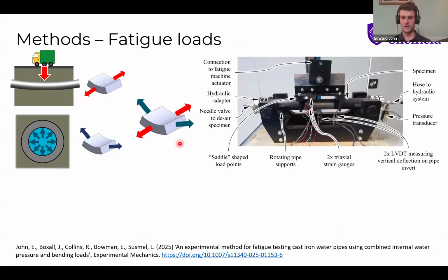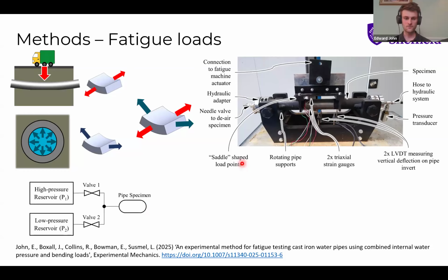So to apply the bending load, we built this piece of 4-point bending equipment. You can see a pipe specimen in the middle there. And so we can bend the pipe and create a high stress region at the bottom in the middle there where we expect a crack to form.